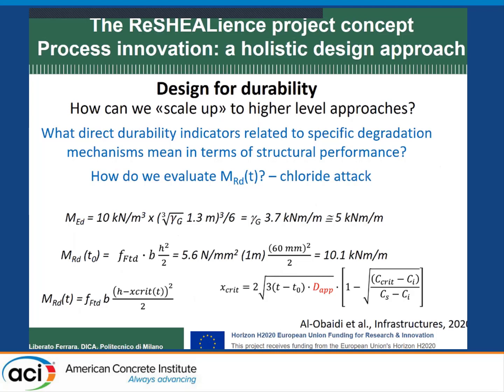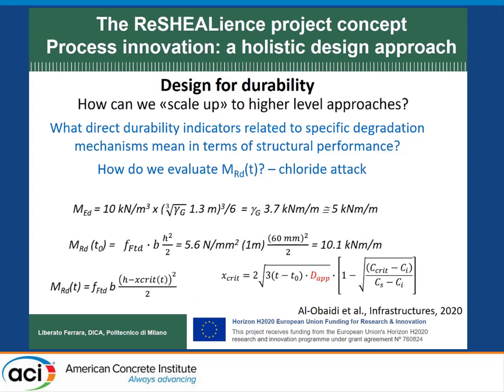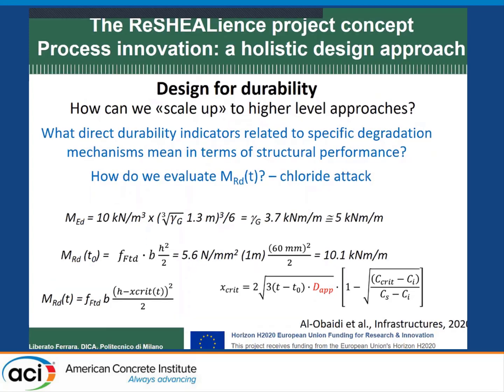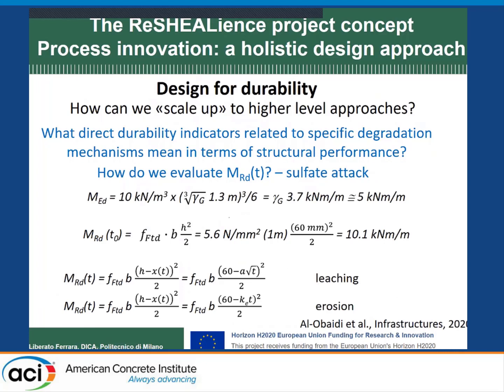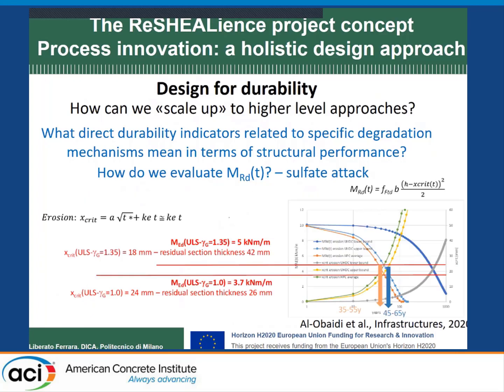But then the durability comes into place. What does it mean? For example, there is a chloride attack and chlorides penetrate. We use a very, very severe approach, in the sense that as long as the chloride critical front penetrates, we remove that layer. So actually, we calculated the evolution of the resistant moment capacity over time by subtracting the chloride penetration front from the initial thickness. Or if we deal with sulfates, we have in the models a leaching model or an erosion model, and we employ the same approach. So you can see these blue, light blue or orange curves are the degradation of the moment capacity with time.